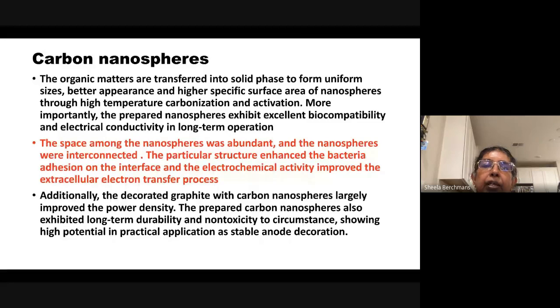So by subjecting organic material like glucose to controlled carbonization and activation, we can get beautiful carbon nanospheres which exhibit excellent biocompatibility and electrical conductivity in long-term operations. Also, it is observed the space among the nanospheres was abundant and the nanospheres were interconnected. The particular structure enhanced the bacteria adhesion on this interface, and the electrochemical activity improved the extracellular electron transfer process.